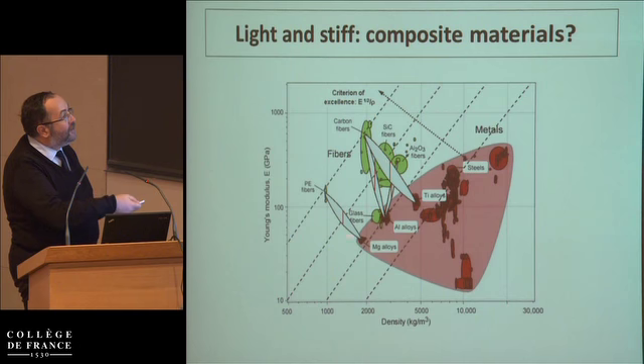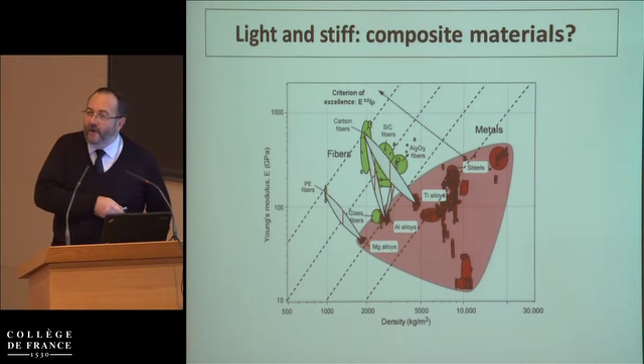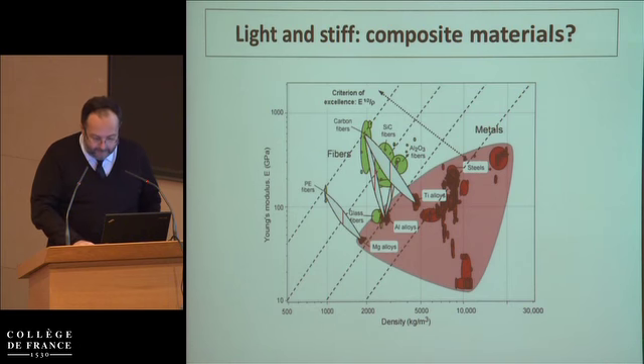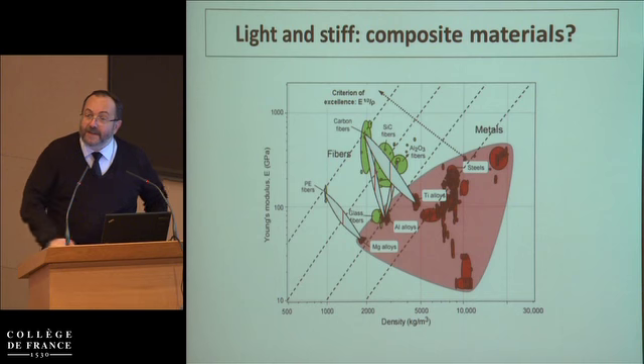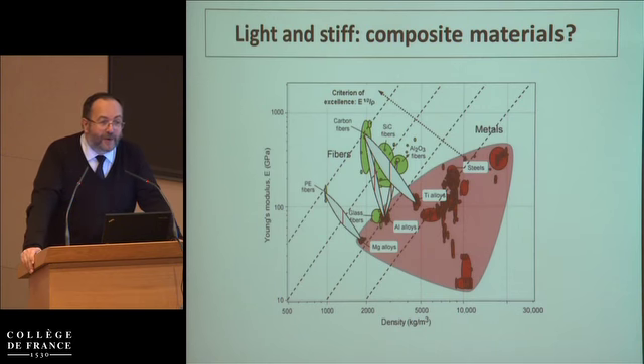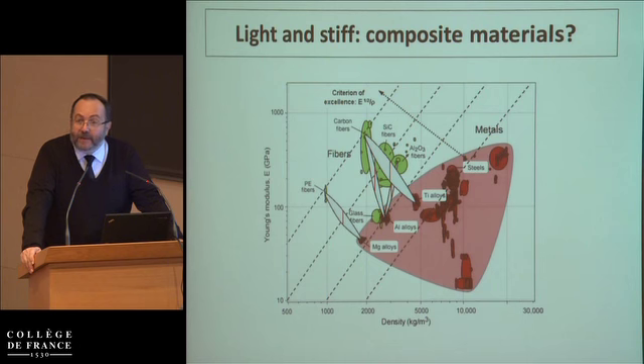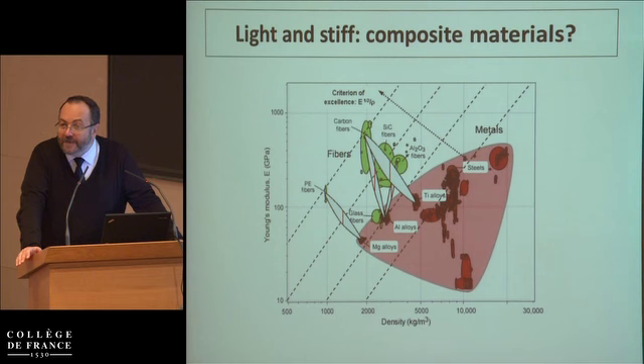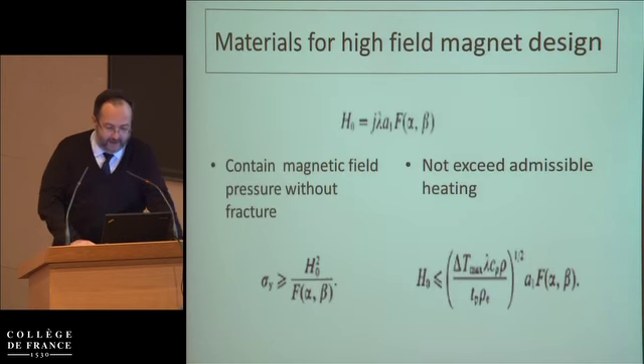So here you will have different ways of making mixtures of titanium or any sort of alloy with ceramics, and these mixtures will give you materials which would have a better, say, E^(1/2) divided by rho property, which would give you the stiffness at minimum weight for a plate, for instance. Now, that's what we call the standard composite. Here, of course, it's purely theoretical because you need to know what is the effect of the mixture between the ceramic and the material, and one ever-coming problem will be the interface between both of them. And we'll have a number of talks about the role of interface in the properties of hybrid materials.